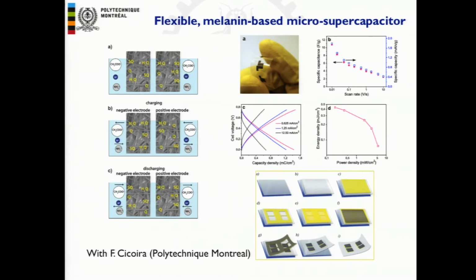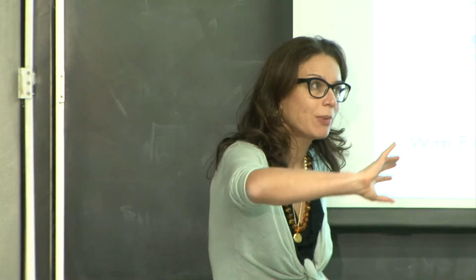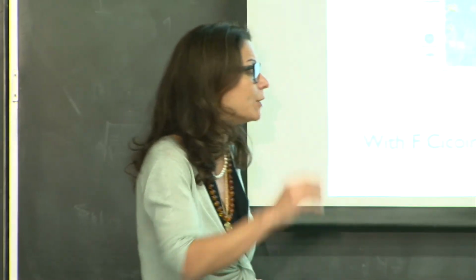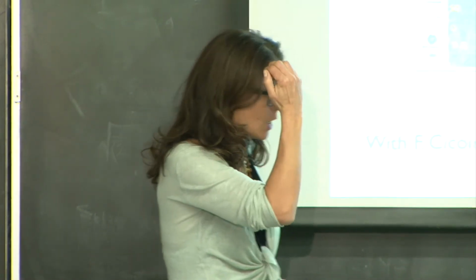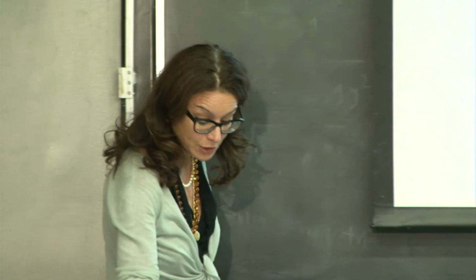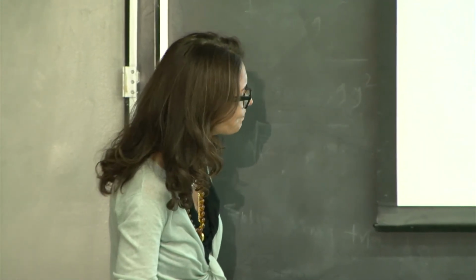After this, we also developed a micro-supercapacitor. I tell you that microfabrication is really an important component of our activity, and we fabricate this device on flexible substrate. The first report was on polyimide, but now we try to do something different. Polyimide works, but we try to go for biodegradable plastics like PCL or PLA, polylactic acid or polycaprolactone, because of their biodegradability, of course.